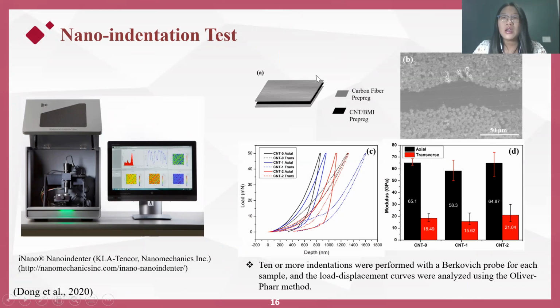I want to note here that the carbon fiber prepreg was designed to provide support because this is a cross-sectional test. From the result here, it is evident that the modulus increased significantly, probably 2 to 3 times when compared to the tensile Young's modulus that we talked about earlier. This is because the tensile properties are more sensitive to the load transfer between the CNT and the resin matrix compared to the compressive properties reflected in this nanoindentation test. Interestingly, the anisotropic ratio from the nanoindentation of CNT BMI composites was also around 3. This is very similar to what we have observed from the tensile and the electrical conductivity measurements.